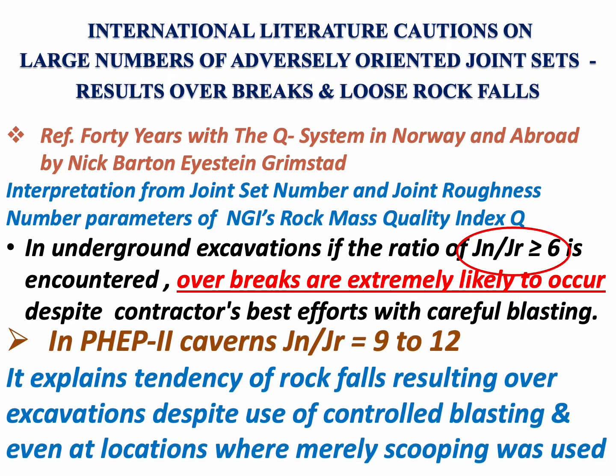In Punatsangchhu-II project, the downstream surge cavern has Jn by Jr ratio of 9 to 12 as against this threshold of 6. This ratio in Punatsangchhu-II downstream surge gallery is 9 to 12. So it explains tendency of rock falls resulting from excavation despite use of controlled blasting and even at locations where merely scooping was used for progressing in tunneling.